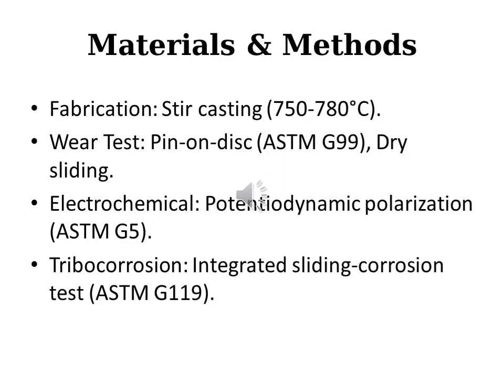In slide 4, materials and methods. Moving on to our methodology, we use stir casting at a temperature between 750 and 780 degrees Celsius for fabrication. For testing, we conducted dry sliding wear tests using a pin-on-disc setup according to the ASTM G99 standard. Electrochemical behavior was analyzed via potentiodynamic polarization, and the full corrosion behavior was evaluated using an integrated sliding corrosion test per ASTM G119.